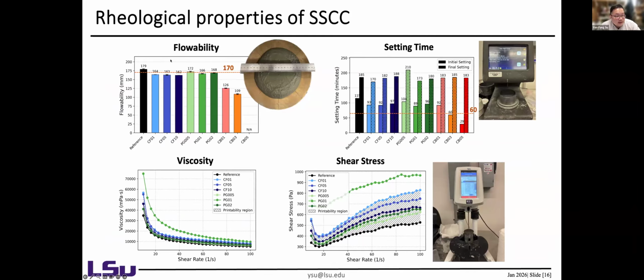For this flow table testing, it shows that the sample with the carbon fiber got pretty good, spreadable, workable flowability, as did the self-sensing cementitious material including the pristine graphene. However, we noticed that the carbon black actually absorbs a lot of water if we use the same water-to-binder ratio for all of the materials. So you need to adjust the water in order to achieve the flowability.